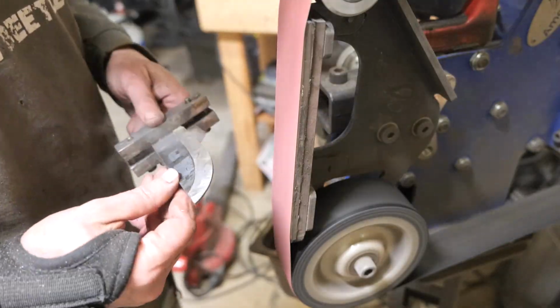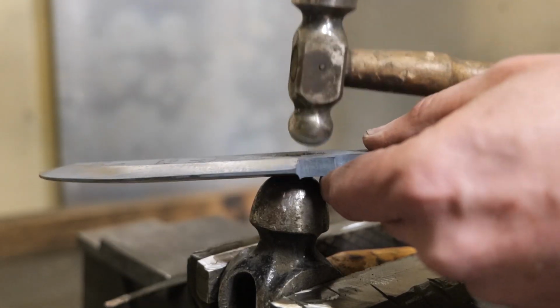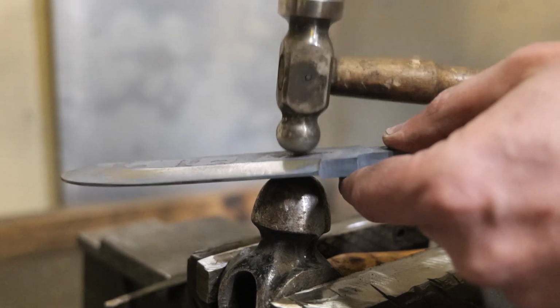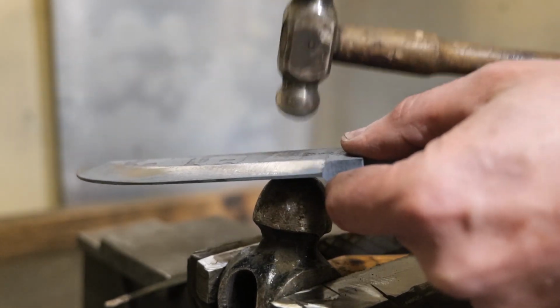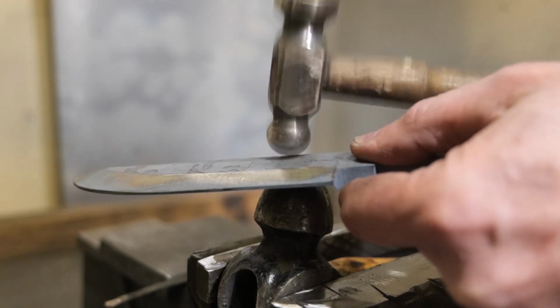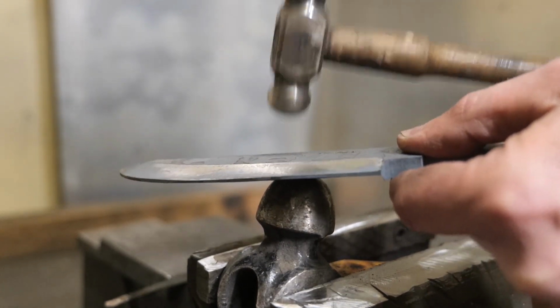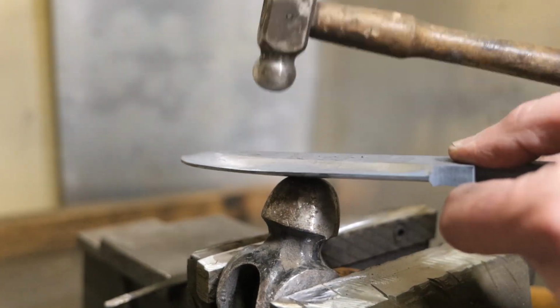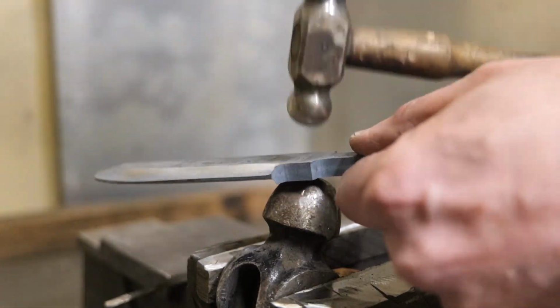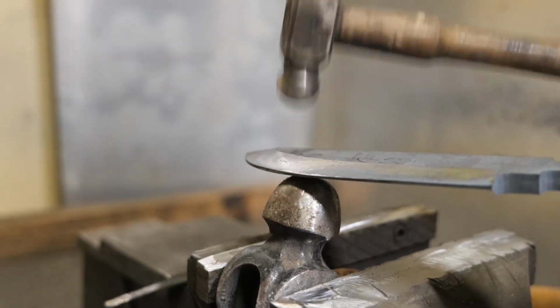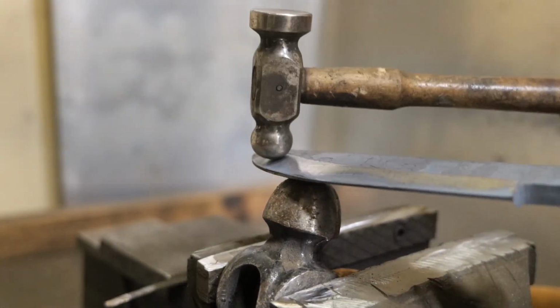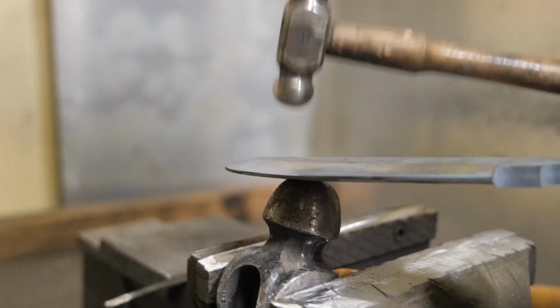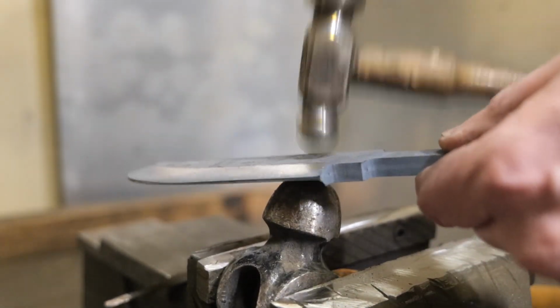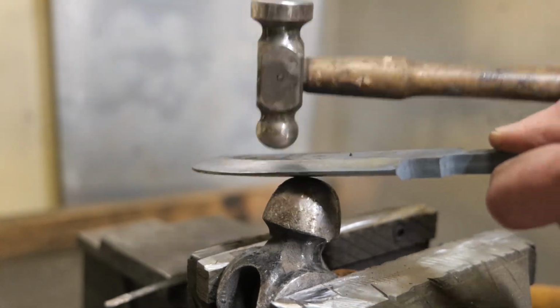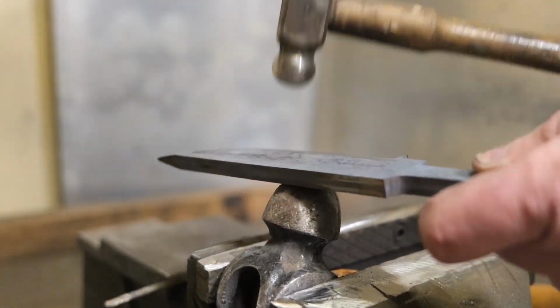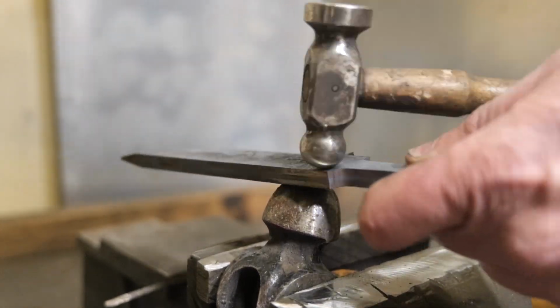So you can imagine that when our sanmai core is moving around that quickly, but the jacket material it's welded to isn't budging, there's a lot of stress created, and in fact it just sort of wants to tear itself apart sometimes. So like we said, the 300 series steels can't be hardened with heat treating, but they do harden cold working, which is why I think people recommend peening the stainless jackets. That may pertain more to 300 series than the 400 series, the 410 that I'm working with. So I don't think this is going to do much here, but a little voodoo can't hurt. Since I don't have a good understanding of it and it can't really hurt, I'm just going to try it.